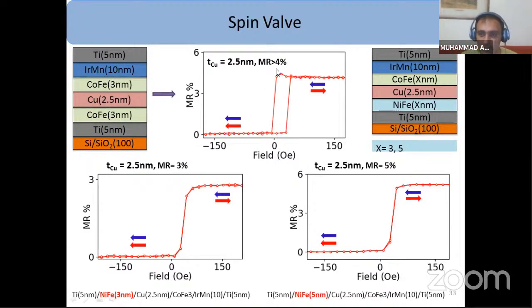I have used nickel iron as a free layer. You can see nickel iron 3 nanometer. I have got a magnetoresistance of 3%, and for a nickel iron 5 nanometer free layer, I have got a magnetoresistance of 5%.